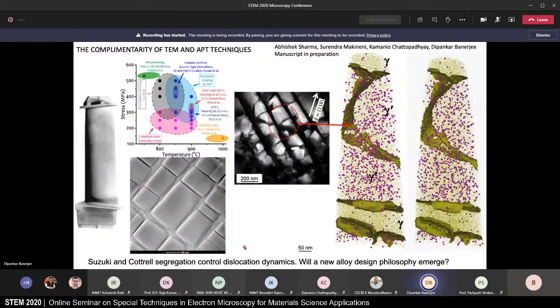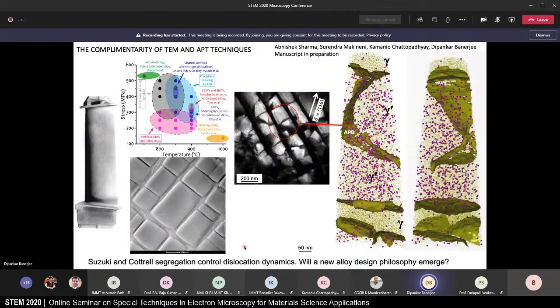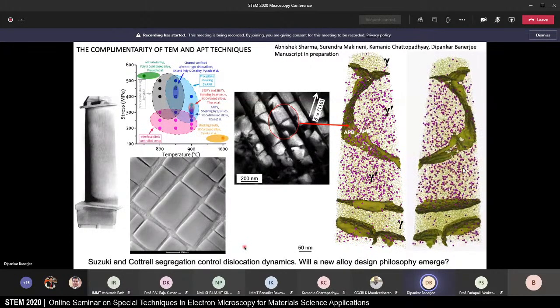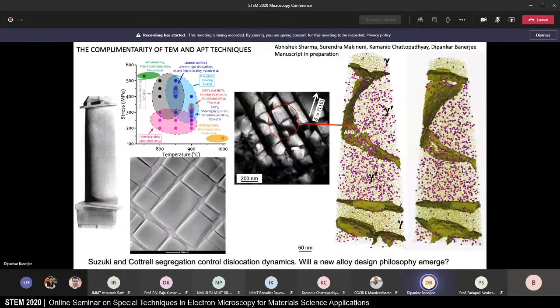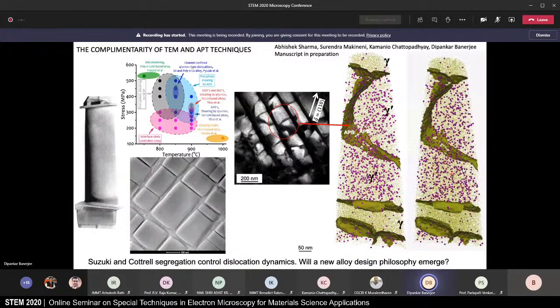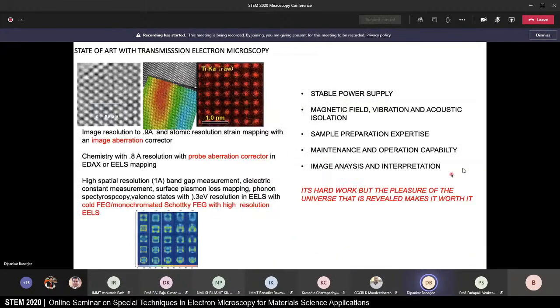So I'm now going to, let me show you that atom probe tomography is also a three-dimensional exercise. So on the right, you have a video which shows you that you can look at this atom probe image in 3 dimensions, unlike most TEM. So let me conclude then, and really conclude by saying that transmission electron microscopy occurs at very different length scales. You can look in basic electron microscopy at the submicroscopic or nanometric length scale. With increasing capability as the instrument has evolved, we can do image resolution to sub-angstrom resolutions. We can do atomic strain mapping. We can do chemistry with sub-angstrom resolutions.